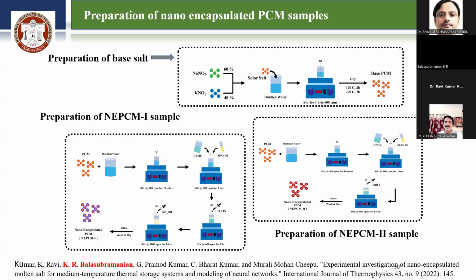So here the NaNO3 and KNO3 are taken, around 60% NaNO3 and 40% KNO3 by weight, and mixed with 500 ml of distilled water. This is stirred in a magnetic stirrer for 1 hour at atmospheric temperature, and then dried in an oven at a temperature between 120 to 200 degrees centigrade for about 2 hours.